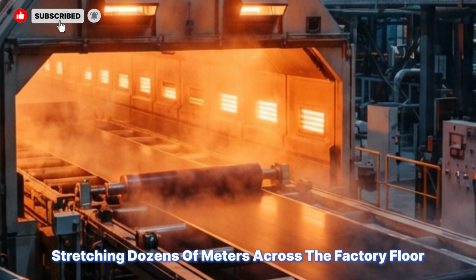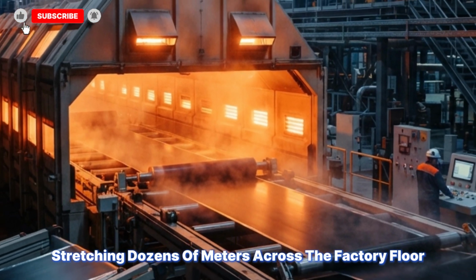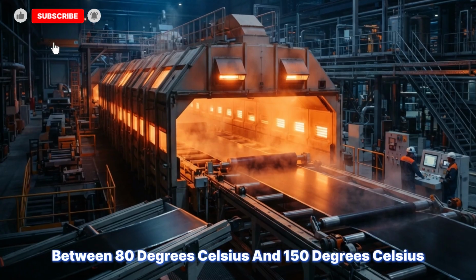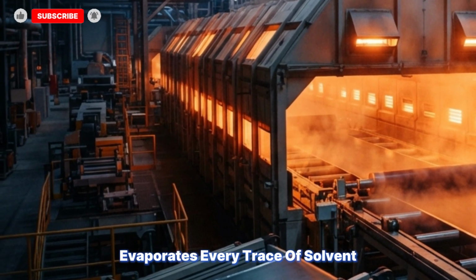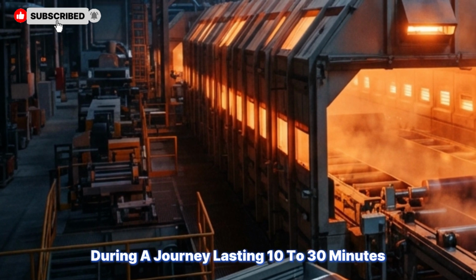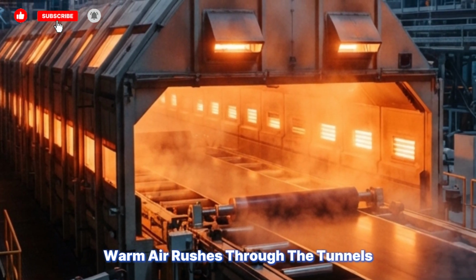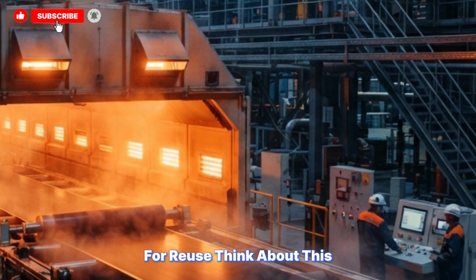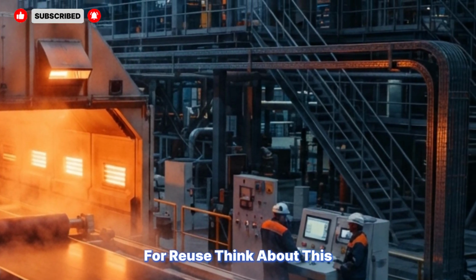Freshly coated electrodes enter drying ovens, stretching dozens of meters across the factory floor. Heated air between 80 degrees Celsius and 150 degrees Celsius, 176 to 302 degrees Fahrenheit, evaporates every trace of solvent during a journey lasting 10 to 30 minutes. Warm air rushes through the tunnels, while sophisticated recovery systems capture valuable chemicals for reuse. Think about this. Nothing gets wasted if engineers can help it.